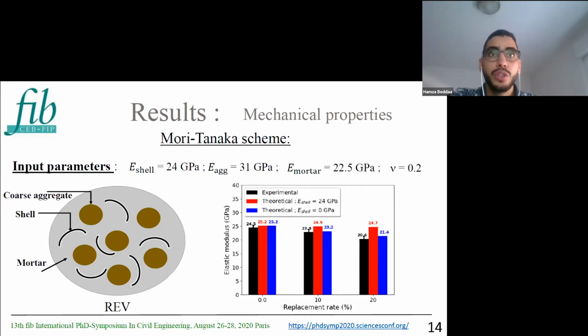So the results show that if we assume a perfect adhesion between the shells and the mortar, the elastic modulus decreases by only 2% for a substitution rate of 20%, while the assumption of a detachment between the mortar and the shells gives elastic modulus values close to those measured experimentally. So it can be concluded that the decrease in elastic modulus with the incorporation of shells can't be attributed to the low modulus of shells, but rather to the weak adhesion between the shells and the mortar.